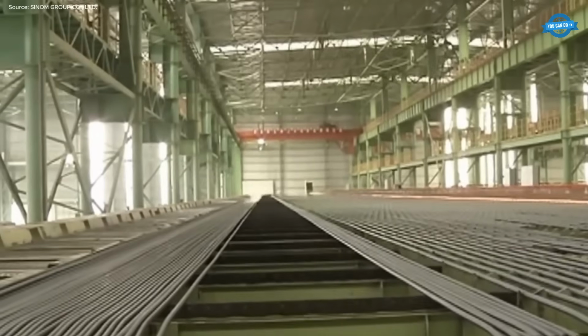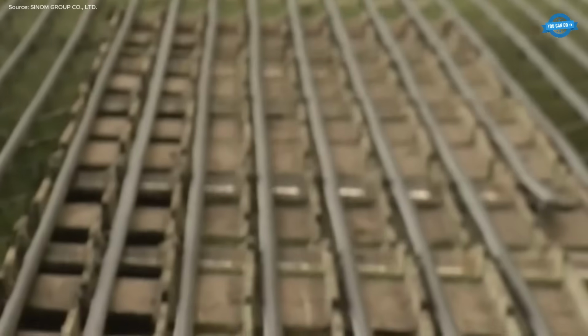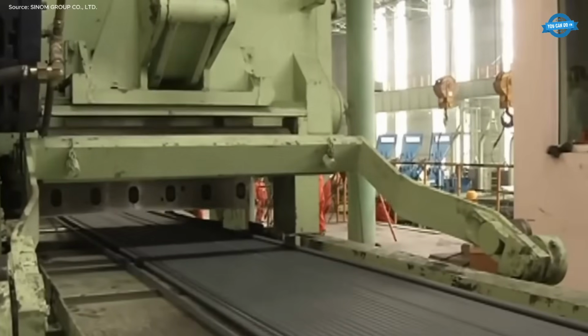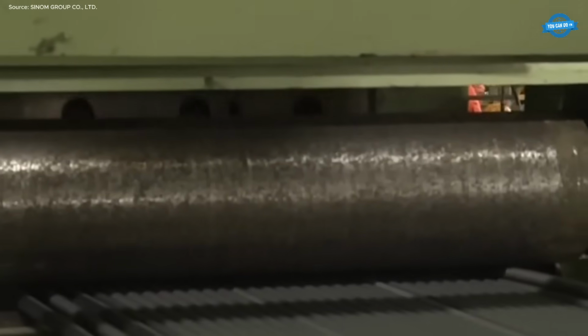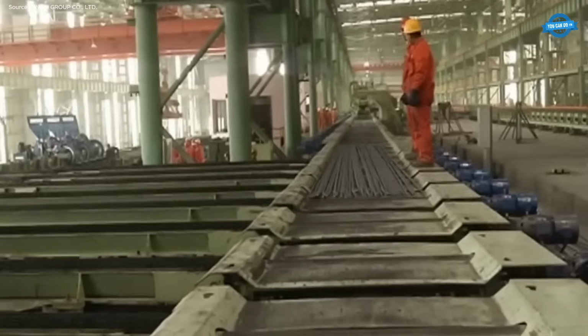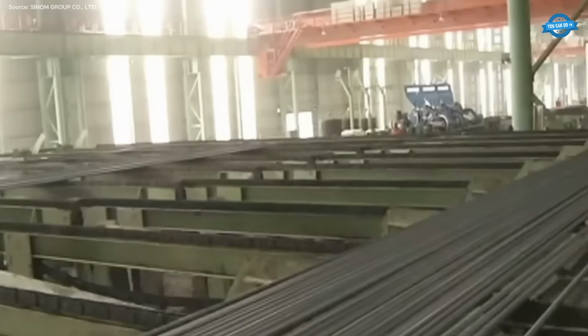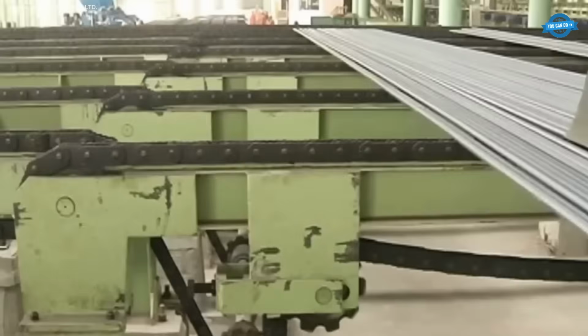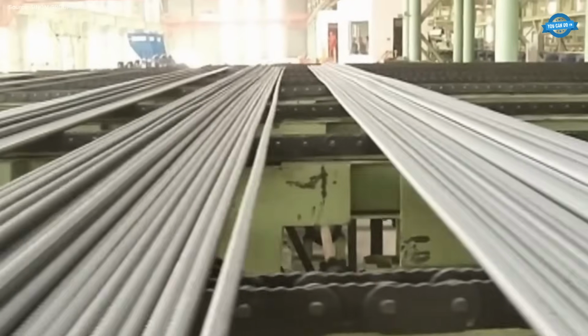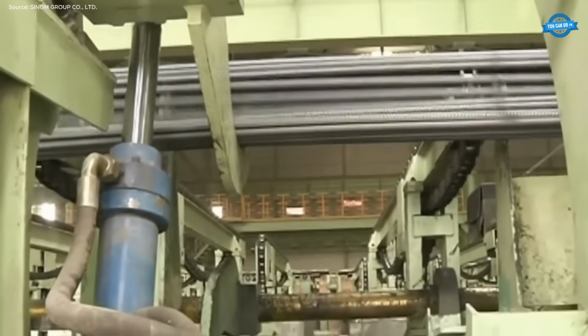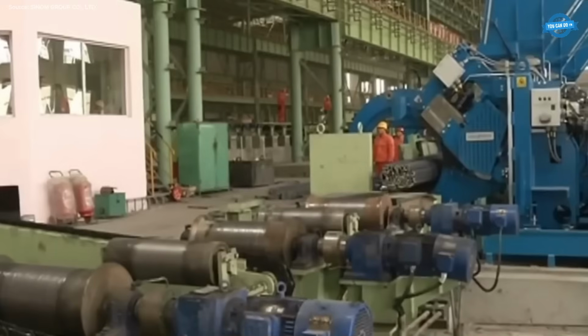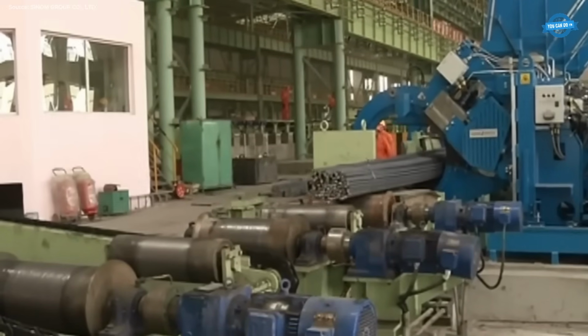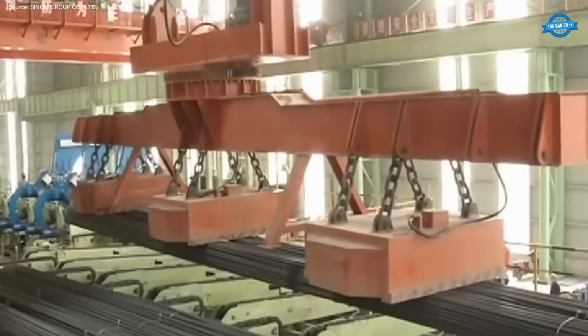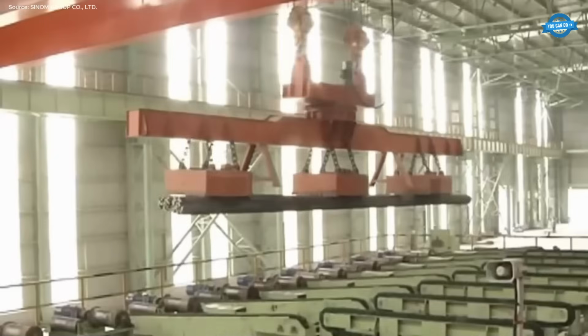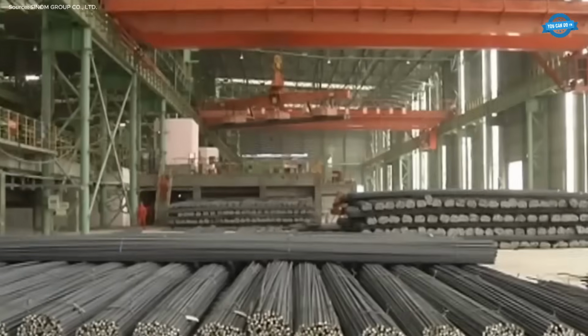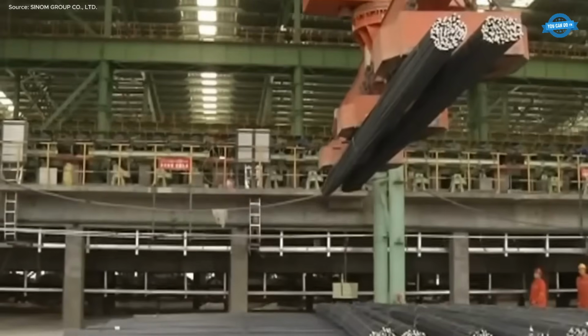enables one billet to be longitudinally divided into 2 to 4 strands using specialized roll passes and guiding systems. These strands are simultaneously rolled to final size and cut at high speeds, up to 20 meters per second for dual strands and 15 meters per second for triple or quadruple strands, before being transferred to the cooling bed. The result is a cost-efficient, high-output line tailored for both construction and alloy steel applications.